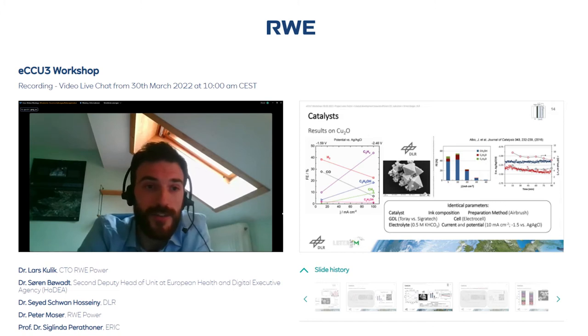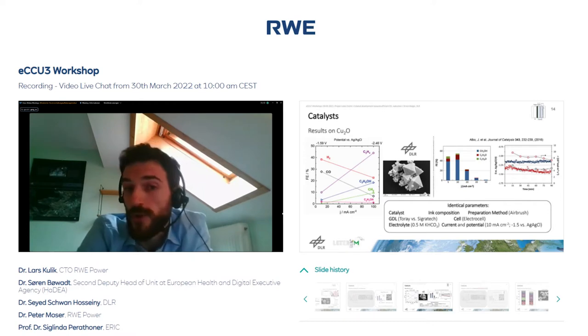So on the left side, you can see at 10 milliampere per square centimeter, our main product is carbon monoxide and some ethylene and more hydrogen, while the paper showed here 40% methanol, even though we used basically the same material. But interestingly, going to higher current densities that you can see also on the left graph at 100 milliampere per square centimeter, we had significant amount of ethylene and also 20% of ethanol and some methane, which was quite